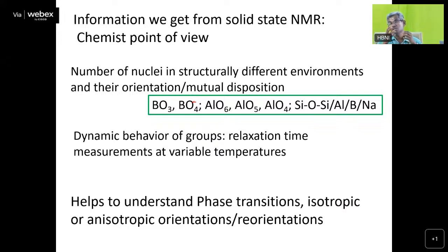The groups move. So groups move means what happens? The relaxation time gets affected, and also, as I mentioned earlier, the dipole-dipole interactions get affected. Once the dipole-dipole interaction gets affected, then we see the modulation of the dipole-dipole interaction, and this modulation leads to changes in the line shape as well as the chemical shift values. And the third and most important is that it helps to understand the phase transitions.